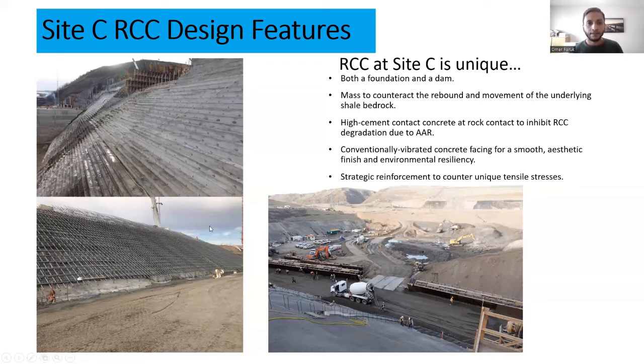And also, as I said, we have a dam feature. In that dam, because concrete is very weak in tension, we needed to increase our tensile capacity for the dams. So when we did our flow study, and then our finite element analysis for the dam, we found some locations that were very critical and weak in tensile strength. So we strategically added some reinforcement to counteract those tensile stresses.